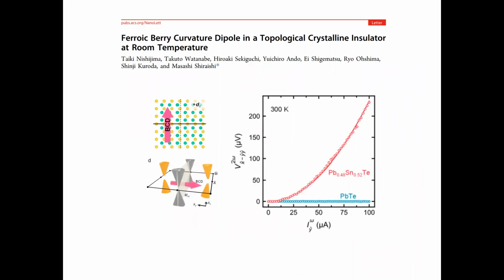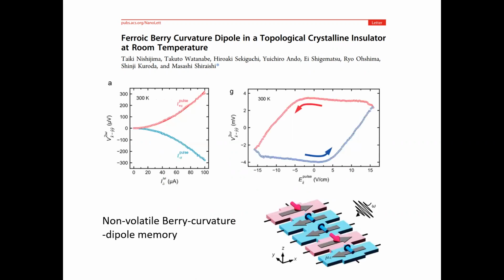And just earlier this year, this experiment came out from Japan. And again, at room temperature, they observed this nonlinear Hall effect. It shows up in lead-tin telluride, which is in the topological regime, but it's clearly absent in lead telluride, which is known to be non-topological, right? Moreover, the sign of the Hall voltage switches when we change the ferroelectric distortion.